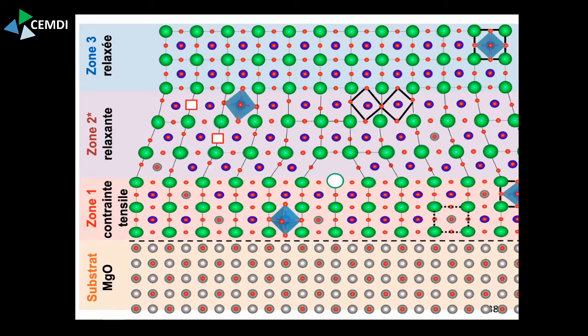So what happens at some point is you create plastic deformations inside your material, in particular these misfit dislocations here, where you have a larger lattice spacing above than below. And for that matter, you create these voids here where one of the atoms has a lower or possibly higher coordination number, depending on what direction your strain goes. And so you get different electronic properties, but you also get very different mechanical properties here.